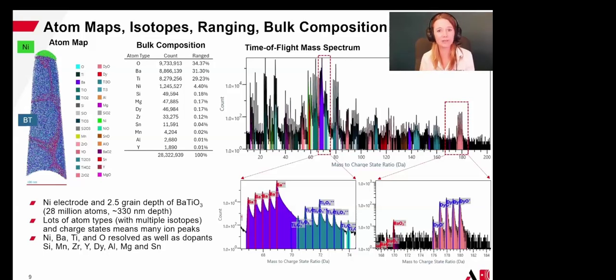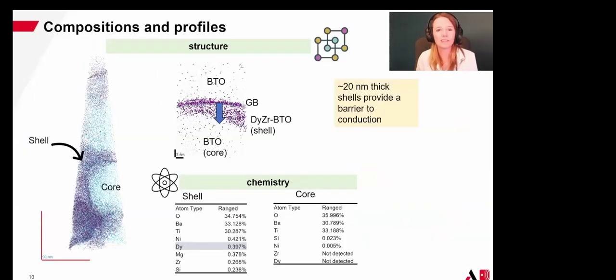So we can take a closer look at how those dopant elements might be distributed. So let's keep in mind our overall goals of this analysis is to look at the chemistry and look at the structure and particularly how these dopant atoms are distributed. Now the first thing that we can see here is pretty clear evidence of core regions, which is a relatively dopant-free regime, kind of circular or maybe even a little bit faceted in nature, surrounded by a shell of doped regions.